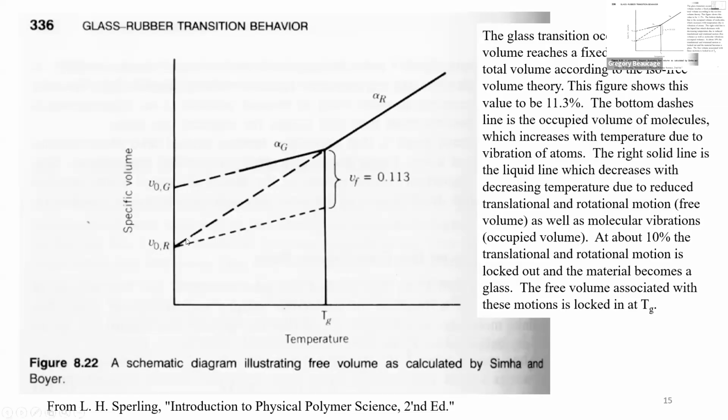So basically this idea of free volume in a glass transition is more than just an idea at that point. You can measure it. You can measure this free volume, right? And you can measure how it changes with temperature. You can measure how it changes between a glass and a liquid, right? So you can get the information that's on this kind of back of the envelope sketch. You can actually measure these things with this positron annihilation thing.